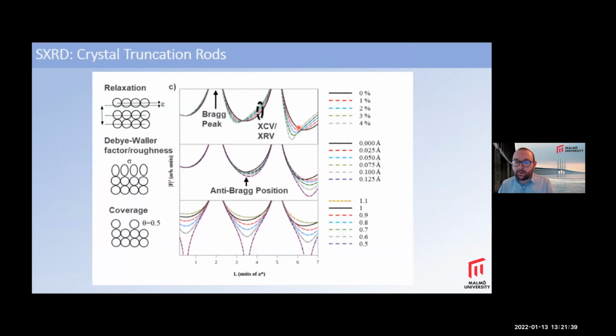I'm of course going to talk about SXRD, and I think most people here are very, very familiar with that. But essentially, you can measure these crystal truncation rods, and by fitting the profile of these crystal truncation rods, you can determine various changes in the structure of the interface. So things like surface relaxation have a different effect than maybe changing the coverage. And so you can construct models and hopefully extract some useful structural information.